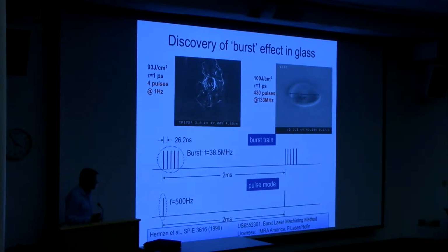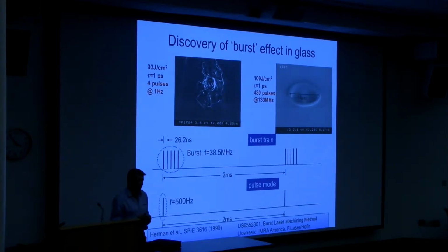And so when you think about it a bit, you realize that the community missed the idea that there's a thermal process associated with femtosecond processing. All the literature before this said it's a non-thermal process, too fast for thermal physics. Well, what happens is, after a first pulse, you've got a heated form of glass that's cooling. It doesn't cool infinitely fast. And the second pulse, if it arrives fast enough, is hitting heated glass. And we know that glass, like all brittle materials, becomes ductile as the temperature rises. And so that ductility prevents cracks from forming and propagating.